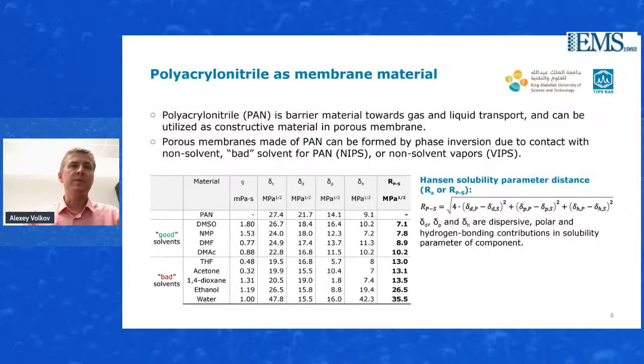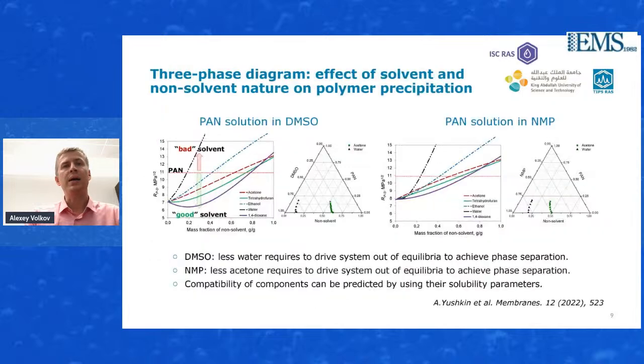And there is a list of good solvents and bad solvents which can be used for dissolving the polymers and also for their precipitation. I'd like to point out that it's worth using the Hansen solubility parameter distance to estimate how we can cast the membrane by the NIPS method. And on the next slide, I will show that. Please apologize for the small graph. There was a last minute change because the system does not support animation.